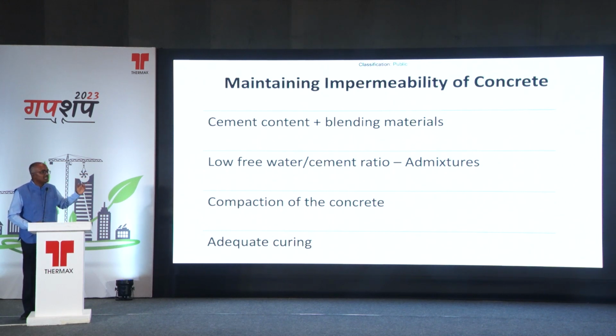But then cement content plus blending materials. This all of us know, blending material like fly ash and slag. But the problem is many of the specifications that are there, there have been a lot of changes over the years, but still a lot of things have to be done. The usage of blending material is not from an environmental perspective alone, but it also enhances the quality in terms of lower heat of hydration, and in terms of ensuring that the concrete is impermeable, because the CSH gel gets strengthened, and the calcium hydroxide, the free lime, gets reduced because of the reaction of fly ash or slag with those materials.